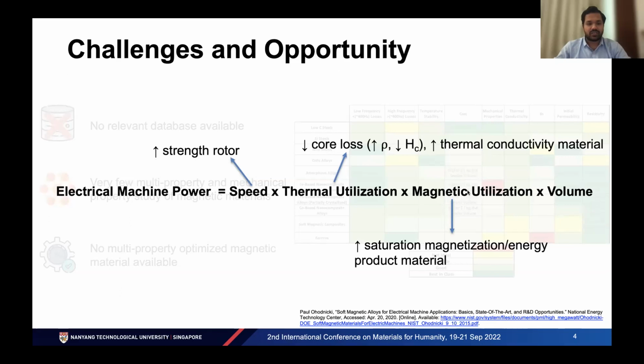Now, as I said, we are focused mainly on electrical machine applications. The electrical machine power can be represented by this formula shown here. In order to develop high rotating speed electrical machines, firstly, we require a high strength rotor. Then we would also require high thermal utilization. For that, we would require low core loss. In that case, we would require high electrical resistivity and low coercivity to reduce the core loss.